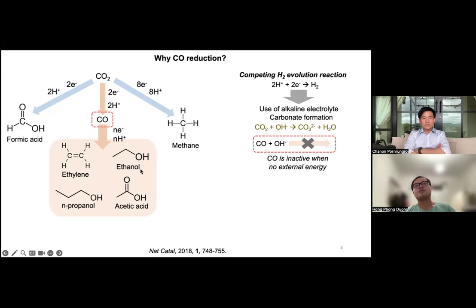It is very difficult to get the oxygen molecule or the oxygen species into the carbon chain and make it stable. Also, achieving this at high efficiency is very challenging from the point of view of thermodynamics. Another thing is that in CO2 reduction research, we usually utilize alkaline electrolyte.